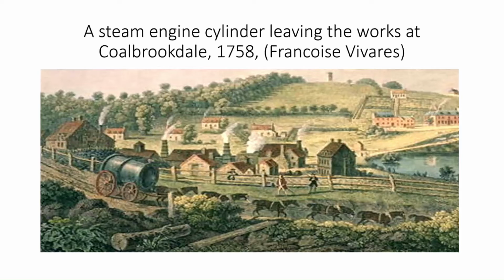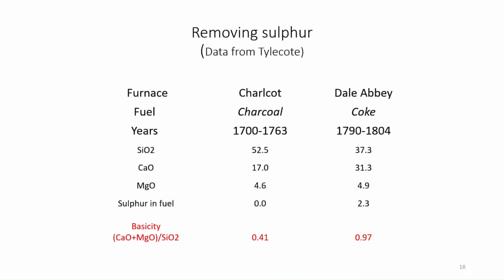Okay, so how was it that simply increasing the hearth temperature of the blast furnace was able to remove sulfur? It was all down to the amount of lime that you could use in the slag. They'd always added lime as a flux, even to charcoal blast furnaces, because it decreased the amount of iron that you lost in the slag. But the problem with using a higher amount of lime is that the slag has a higher melting point as a result, a higher fluidity point, I think is probably the best way of putting it. In order to remove sulfur, you had to have a higher basicity in the slag, which required a higher temperature to melt it, crudely.